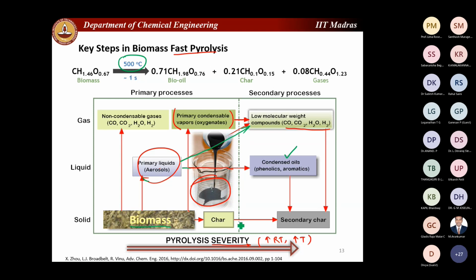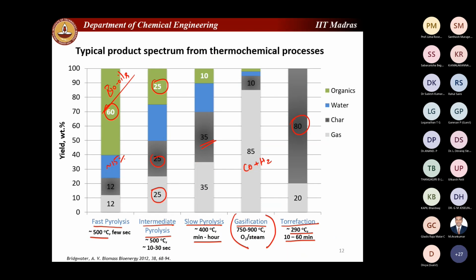And obviously, right, your char and also the aromatic hydrocarbons can polymerize to form much more amount of char, okay, which is sometimes also called as secondary char. It differs in the structure from primary char. So typically, with the increase in pyrolysis severity, that means increase in residence time and increase in temperature, you can actually shift the product distribution. Okay, so that means when you do a slow pyrolysis process, you get very high amount of char, whereas when you do a fast pyrolysis process, you get very high amount of the oils or the bio oil or the organics that are present in the product.